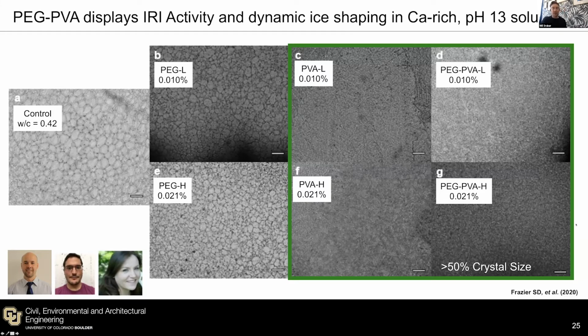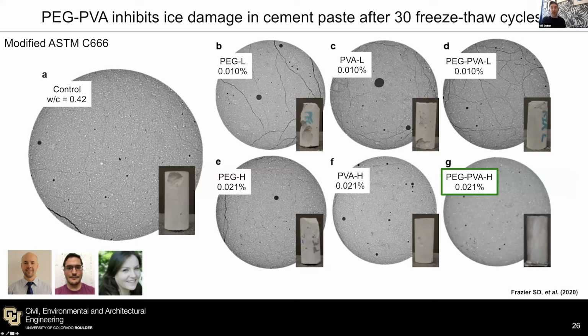And thought, okay, well, let's go ahead and put this molecule in cement paste and see if it resists freezing and thawing. So these are the results. These are microcomputed X-ray tomography images, basically an X-ray cross-section of cement paste samples that underwent freezing and thawing for 30 cycles. On the left-hand side is the sample without the molecule. And then these samples here are with the molecules at low and high concentrations. What we were really excited to find was that PEG-PVA, when added at a slightly higher concentration, did exhibit enhanced freeze-thaw resistance compared to the control samples and all of the other samples that had the molecules in them. This indicated to us that we should go ahead and scale this up to full-scale concrete, which is what we did.